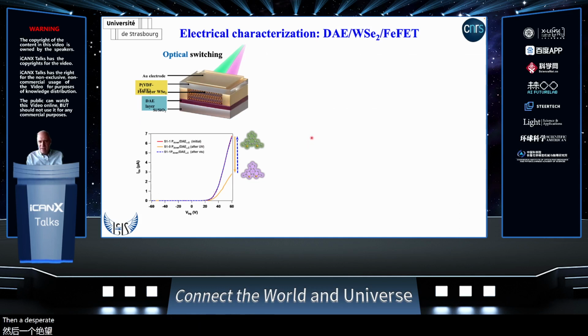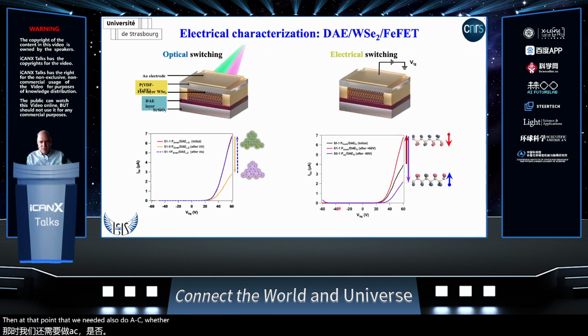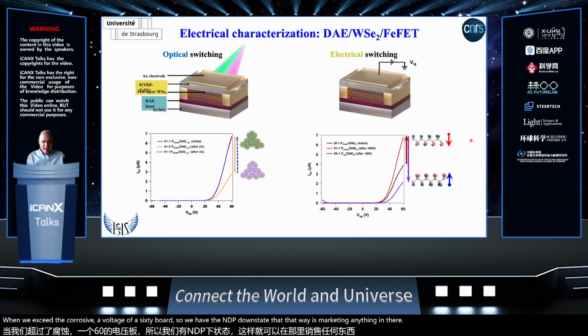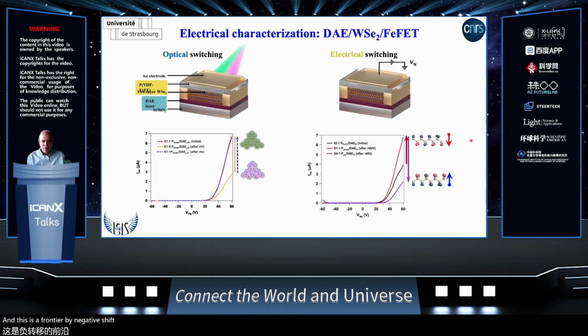Then at that point, we also needed to see whether, in our device architecture, we could electrically switch using the top ferroelectric material. What we observe is that we can access a different state by applying a voltage to the top gate bias when we exceed the coercive voltage of 60 volts. In the P down state, marked in red, obtained upon applying plus 60 volts, we have an increase of the electron current, accompanied by a negative shift of the threshold voltage, whereas when we apply minus 60 volts, the current decreases drastically. We have a modulation of 68% of the current, and this is the case where we have all the P up.